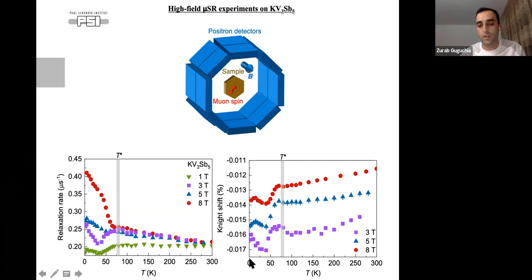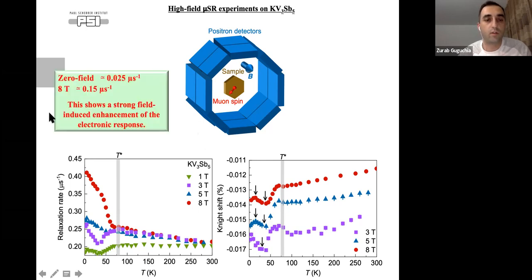And also this is the so-called Knight shift, and this is more like a local magnetic susceptibility. We see the increase, so this is negative here. We see the increase just below the charge density wave transition temperature. And at low temperature, we have some kind of peak. I don't exactly know what it's related to, but it could be related to some maybe nematic susceptibility, which was found for the cesium compound by Ilya Tselkovich and his group. But one has to do some more careful measurements at low temperatures and try to understand this. But at least there's a clear increase of the local magnetic susceptibility below the charge density wave transition temperature.